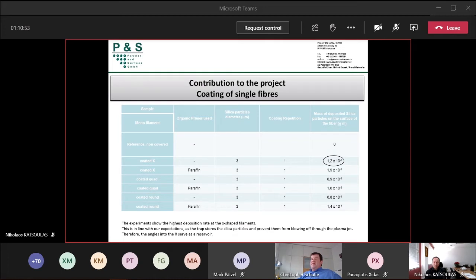And there's another point. We thought a lot about how we can swell, how we can plastify the thermoplast material of the monofilament. And then we found the idea that we can use a swelling agent like paraffin. Paraffin is able to swell the thermoplastic, and then it evaporates immediately with the plasma nozzle, with the flame, and then everything becomes hard again, and the particles are then better fixed. And as you can see here, we have the best results with deposition always with the swelling agent. So it's the second, the fourth, and the sixth.